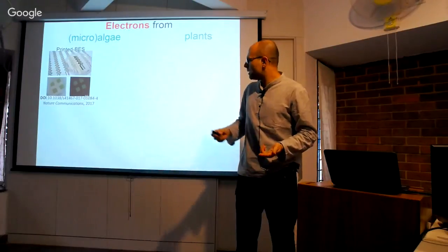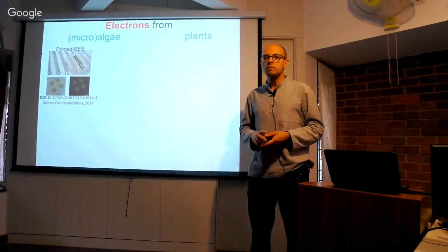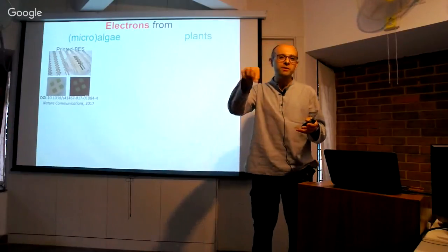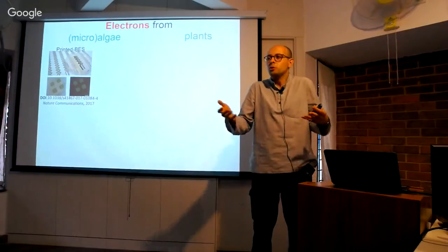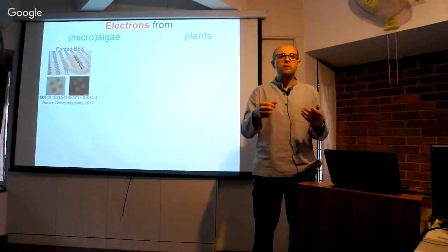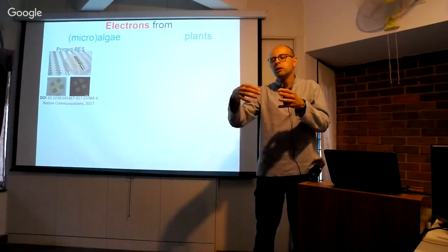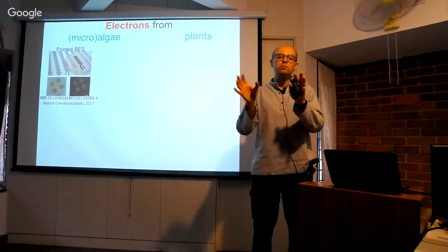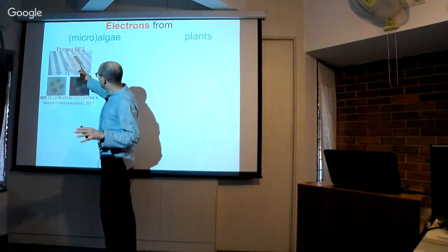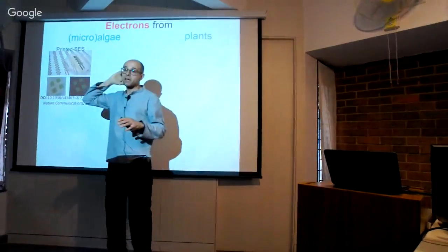For example, in this one, published not long ago, the person in charge of this study, her name is Marin, ended up doing something very, in my view, elegant. She modified a printer, and instead of using the usual ink, she's using microalgae for printing. And she's mixing this microalgae with a powder of conductive carbon. So in this way, she's printing the algae and the carbon together, and that will work as an anode. I'll show you later on what I mean by anode. Just for a visual understanding, this green tray is the print with the algae alone, and the gray one is the electrode.